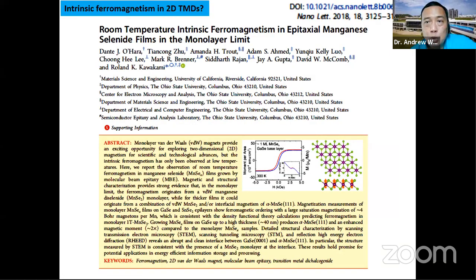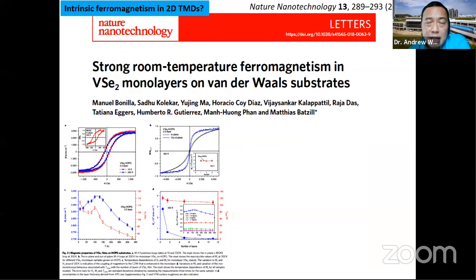This is the paper 2 years ago from Kawakami's group on manganese diselenide, and they showed some magnetism in this monolayer. This was one of the first studies showing magnetism in a transition metal dichalcogenide. Another paper that year in Nature Nanotechnology by the Batzill group in Florida also showed strong room temperature ferromagnetism in vanadium diselenide. And the reason why this excites a lot of people is because it's at room temperature and it's a strong ferromagnetism.